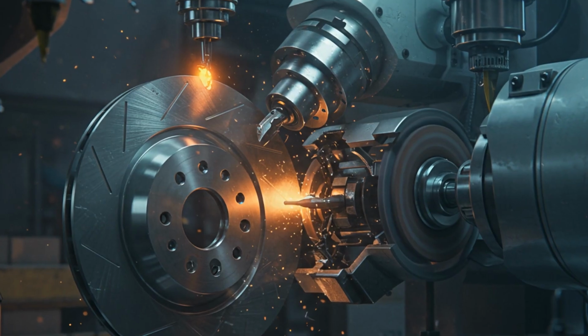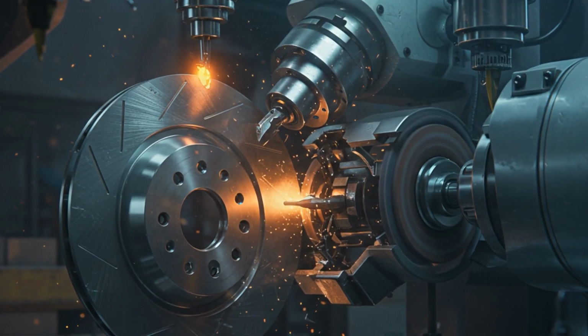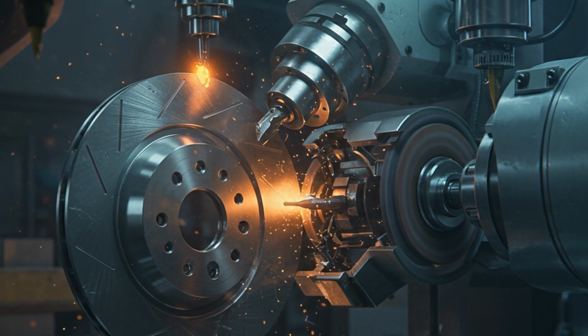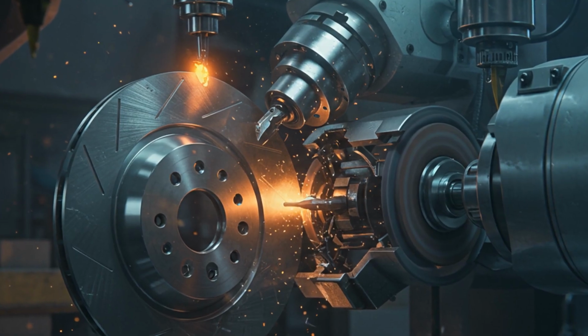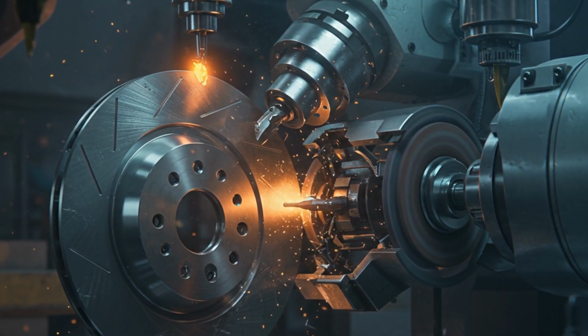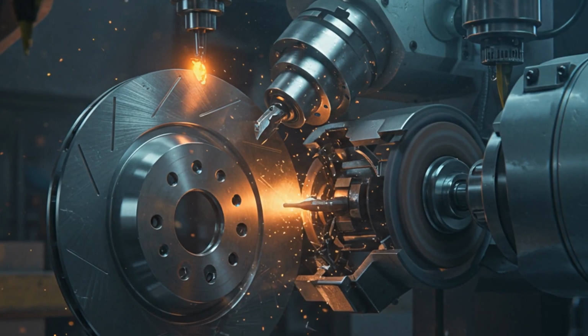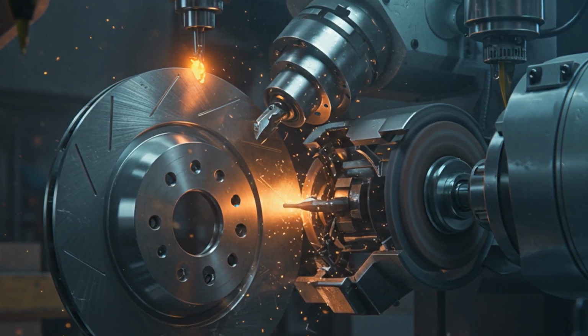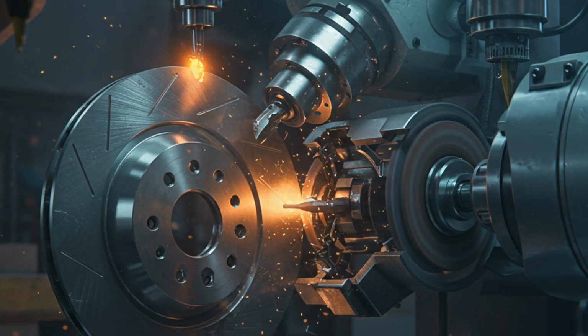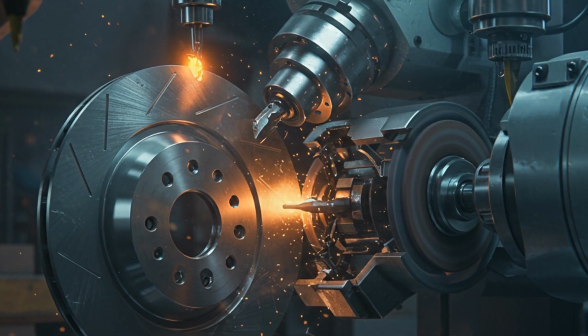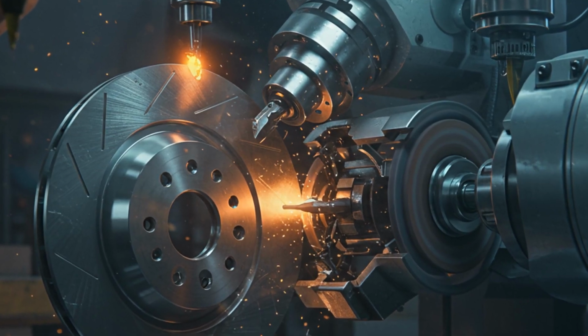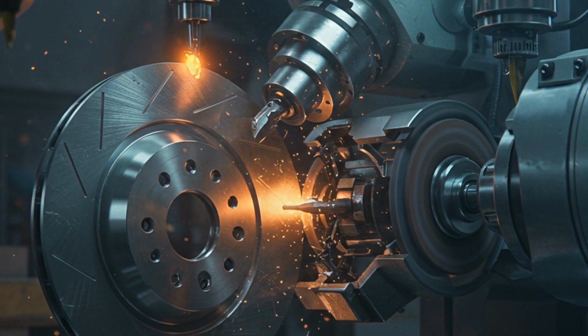Balancing is vital. Rotors are spin balanced at speeds above 1,000 revolutions per minute to detect mass imbalances that would cause cyclic loads. Finally, rotors undergo dimensional inspection, magnetic particle inspection for cracks, and a trial assembly to verify fit. Each step protects one outcome: consistent, repeatable deceleration without catastrophic failure.